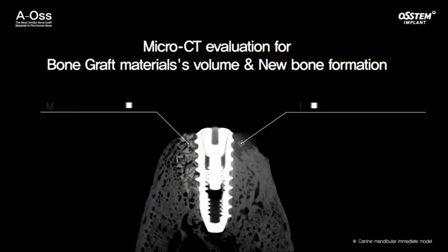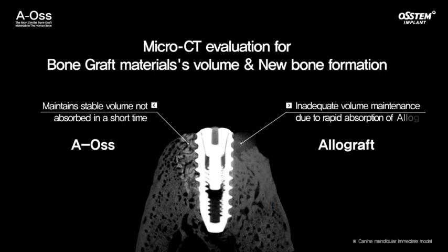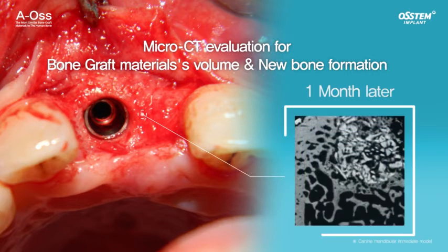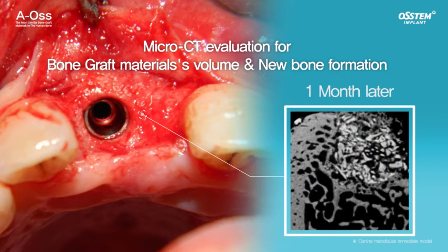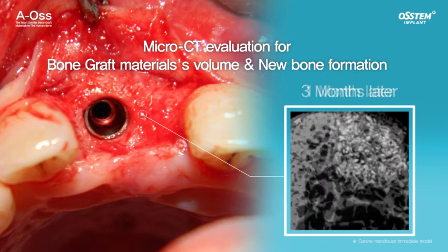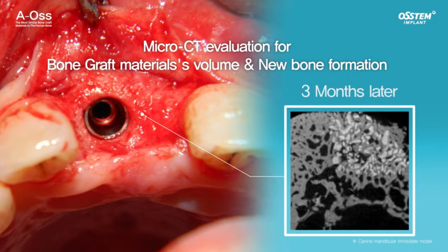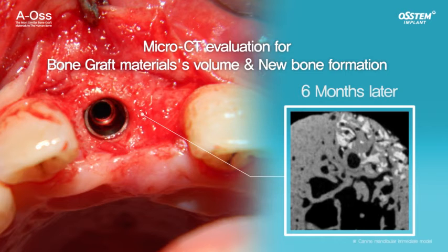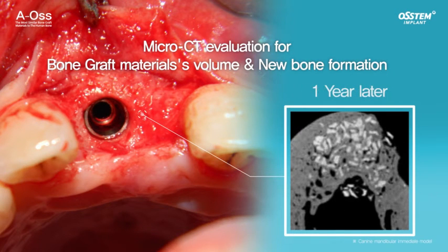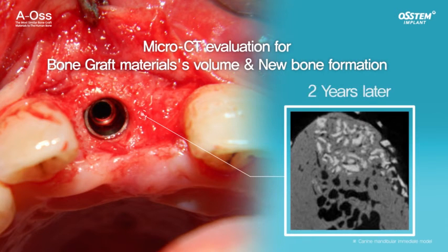A-Oss has excellent structural stability since it is not absorbed in the body in a short time, and it maintains stable volume maintenance until the defect area self-ossifies. As a result of long-term follow-up, A-Oss maintains the height after implantation without volume change for two years of the total implantation period, and shows stable bone formation.